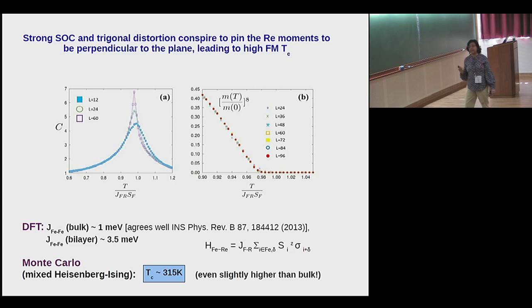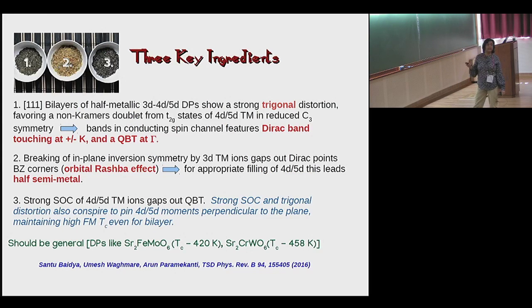So that means we have generated this kind of anomalous quantum Hall state, which is operating at a very high temperature. So to conclude on this part, there are three essential ingredients. First of all, these bilayers of this half-metallic double perovskite, a combination of 3D with 4D or 5D, grown along the 111 direction, show a strong trigonal distortion favoring a non-Kramers doublet, which are basically Eg pi, and the bands in the conducting spin channel feature the Dirac-band-like touching at plus minus K point and the quadratic band touching at gamma, and breaking this inversion symmetry of this iron gaps out the gamma point, which is like the orbital Rashba effect.